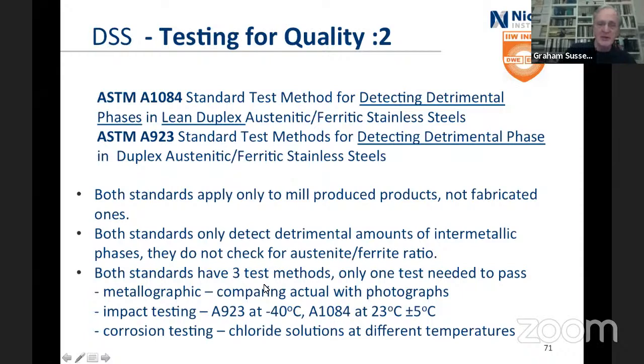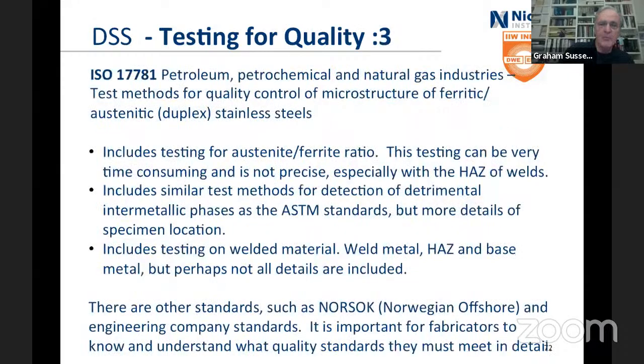There are 3 test methods. Either you do an etched micro and compare it with photographs, you do impact testing, -40 and 23, and you do corrosion testing, different temperatures, and I'm not going to go into those, but it's basically reflecting what happens. Interestingly, the duplex ordinary 2205, there's different temperatures for welded material and for parent material, which I suppose is sensible.